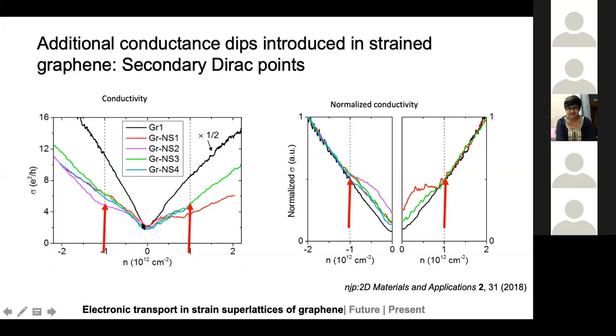But if you have nanospheres present, then there is some amount of strain generated in the system, and that corresponds to these differences. If you plot the normalized conductivity for all the systems, you see that apart from this dip at the Dirac point, which is expected, there are these additional kinks which show up in these regions I've marked with the red arrows. These kinks become more prominent as you increase the strain in the system. So this red and purple curve correspond to more strained graphene devices. And those kinks occur at a carrier density of 10 to the power 12 per square centimeter. And this was observed for all of those strained samples.